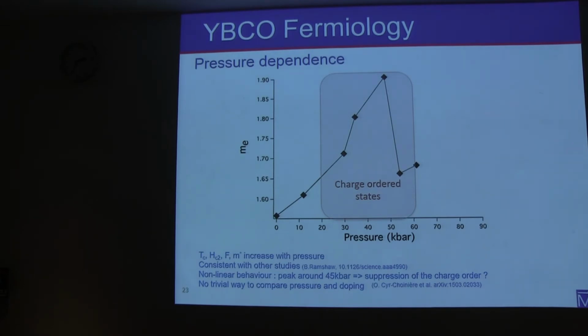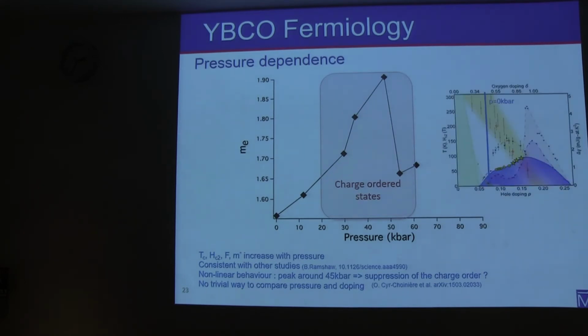And so again, by applying pressure, we change the doping, but not only, we change also other things. So if we compare with the hole doping, at ambient pressure we were about here, and by tuning the pressure, and if we compare with the critical field, we go to about here, this doping with 7 GPa. So we're still below optimal doping, and the next question is, how far in pressure do we have to go to the overdoped side?